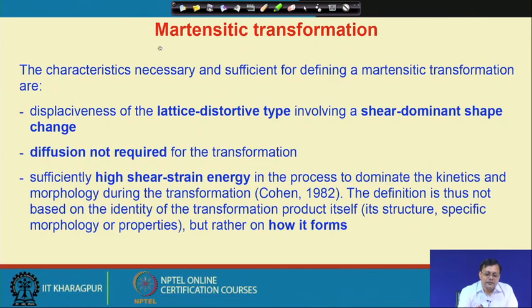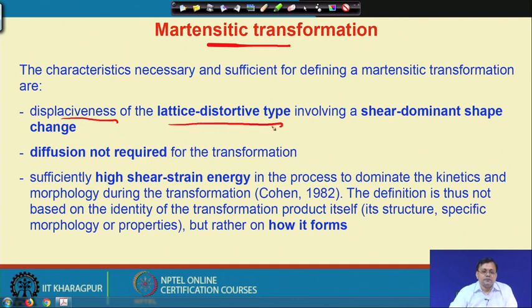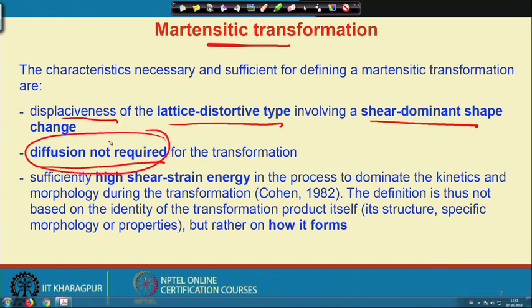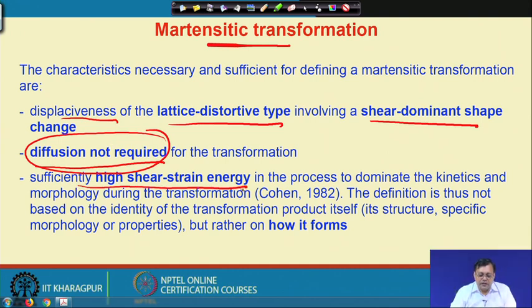Whereas, in case of a martensitic transformation, there are some typical signatures. What we looked at here is the displaciveness, or the displacive transformation, the lattice distortive type. In that case, we see a shear dominant shape change of the lattice. So, there is a definite shape change involved in the lattice, and diffusion is not required at all. There could also be a sufficiently high shear strain energy in the process, which has also been reported by Cohen et al., from a very long time ago, 1982.